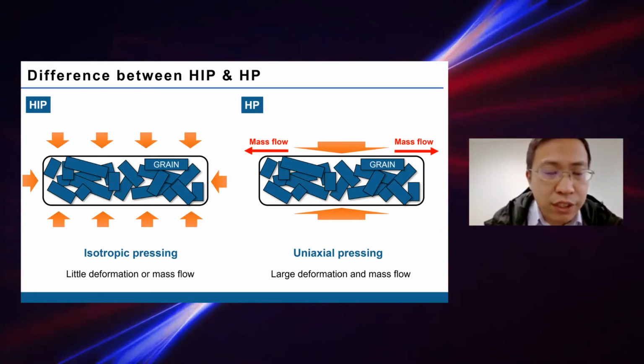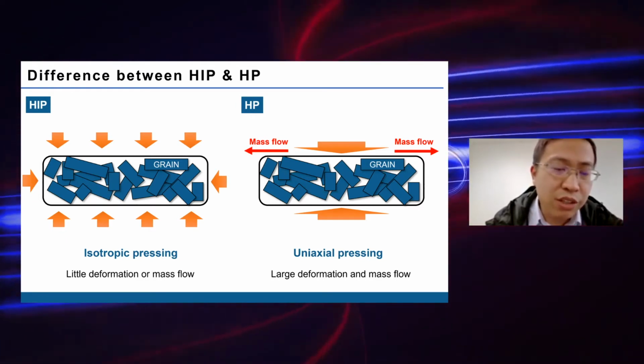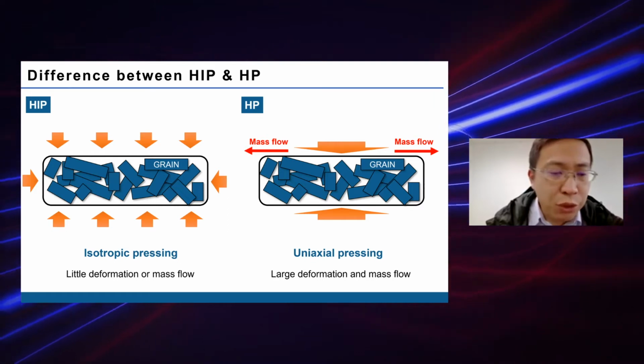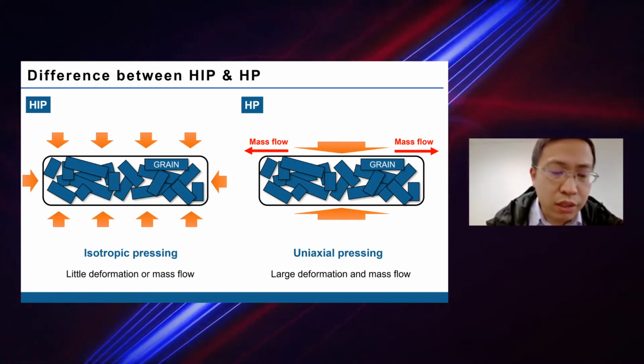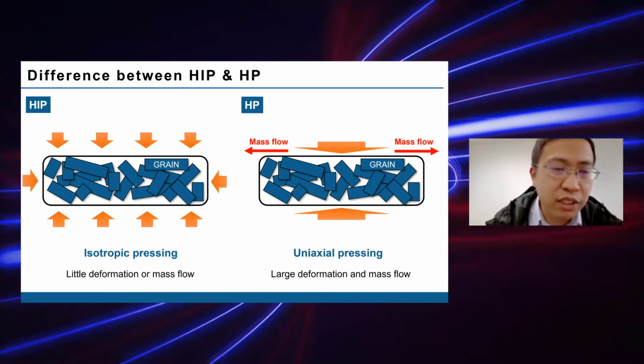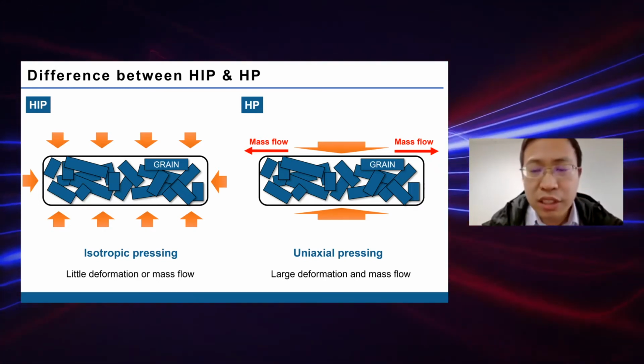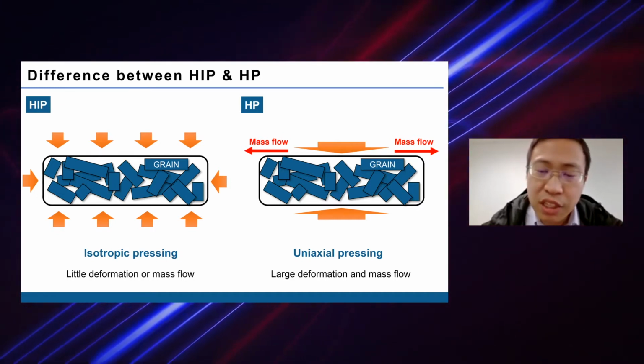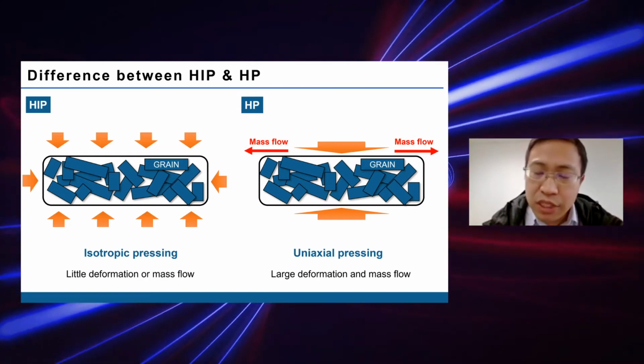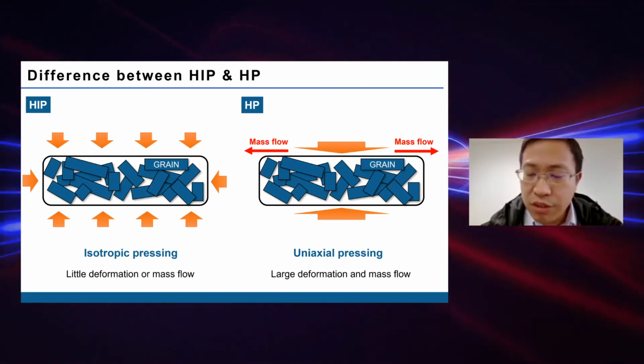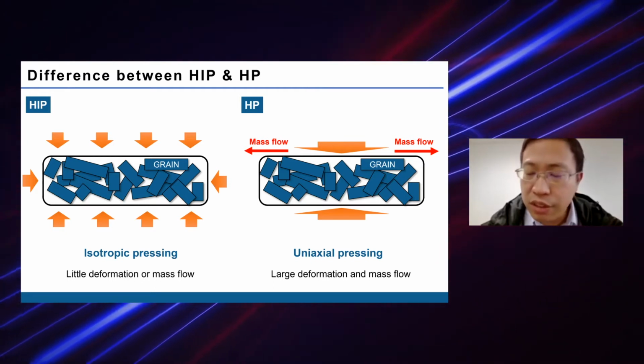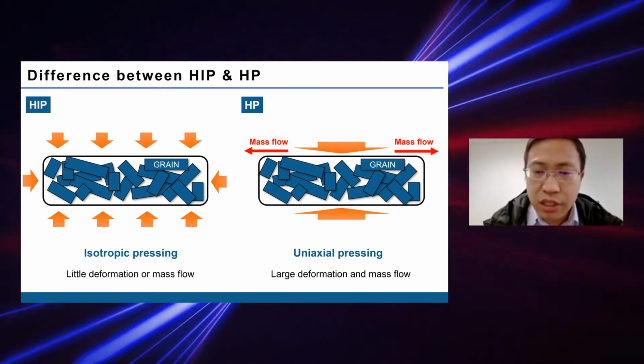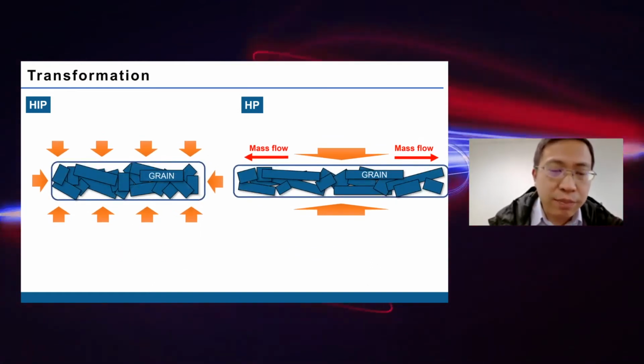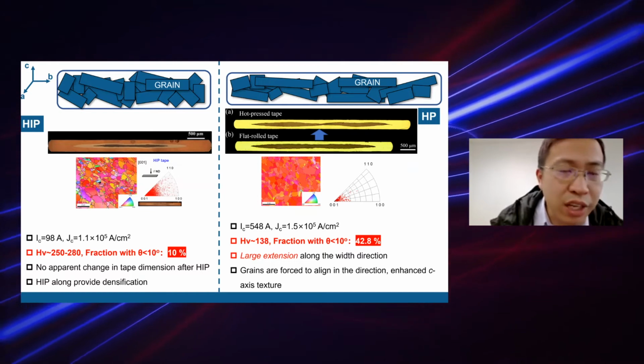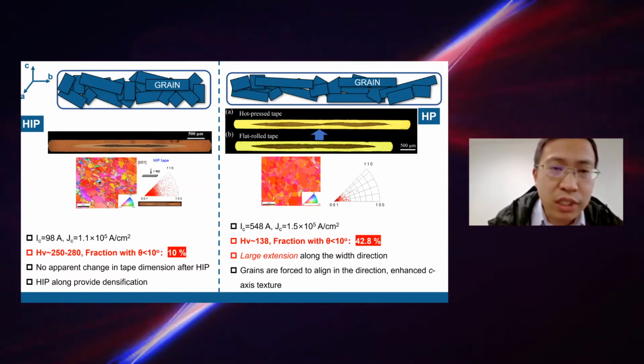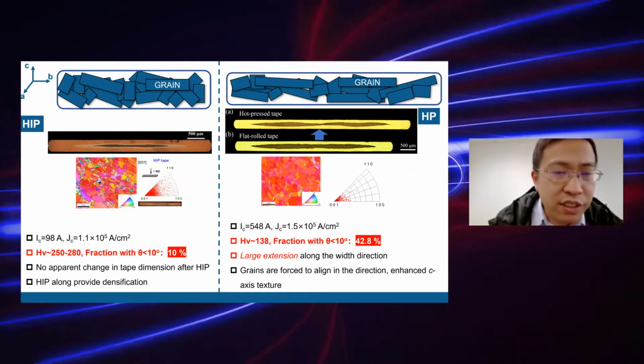For the HIP process, the pressure is actually isotropic. So there is very little deformation and very little mass flow in the HIP wires and tapes. But for the hot press tapes, because there are no limits on the two sides of the tape, we can see a large deformation in the transverse direction and the mass flow also in the transverse direction, maybe like this. And we can see that in the HIP wires and tapes, the grains are more closely connected, but the c-axis texture is not enhanced.